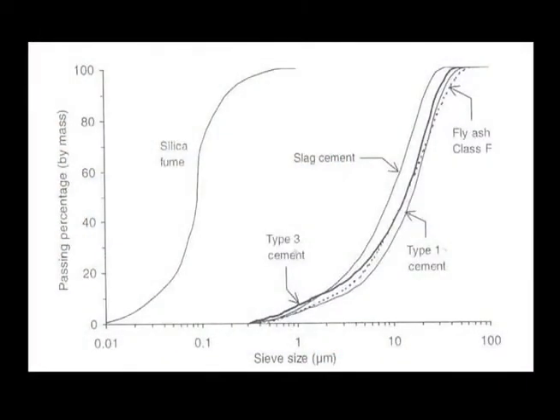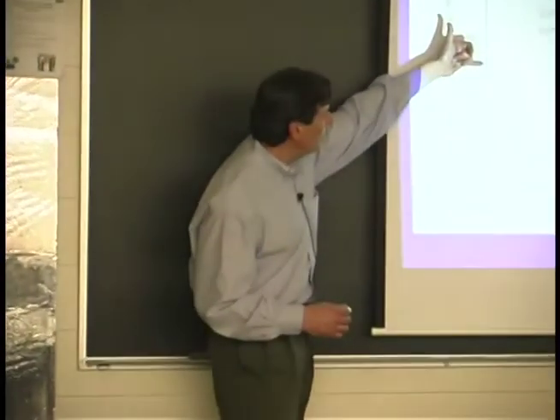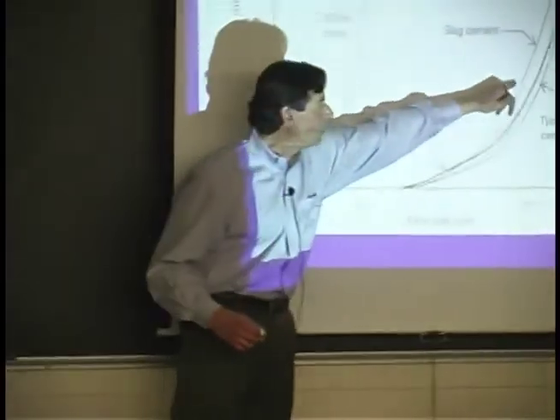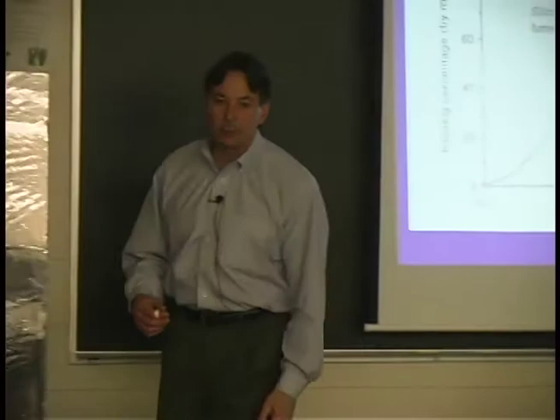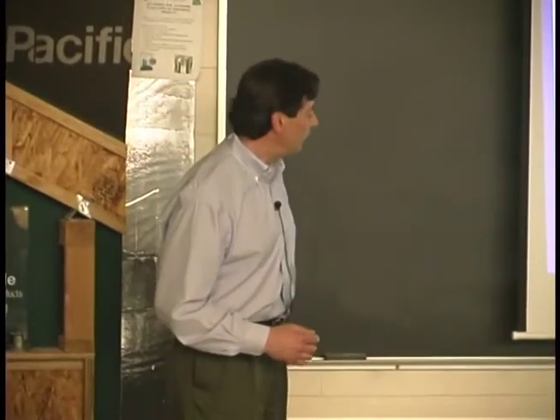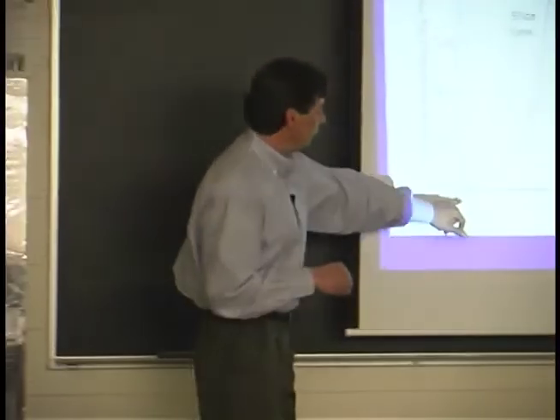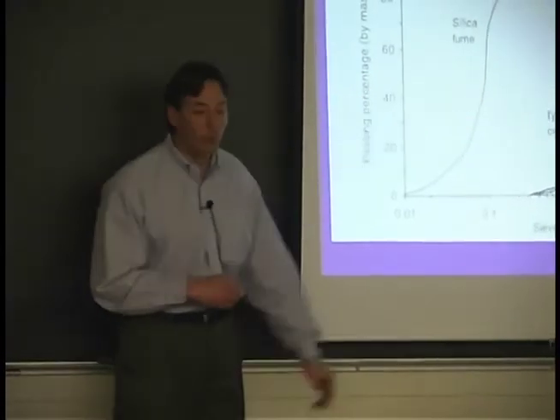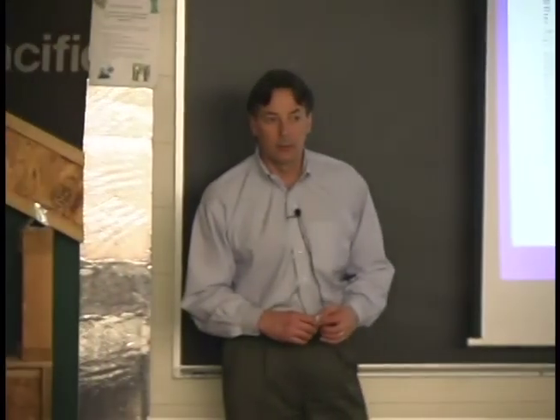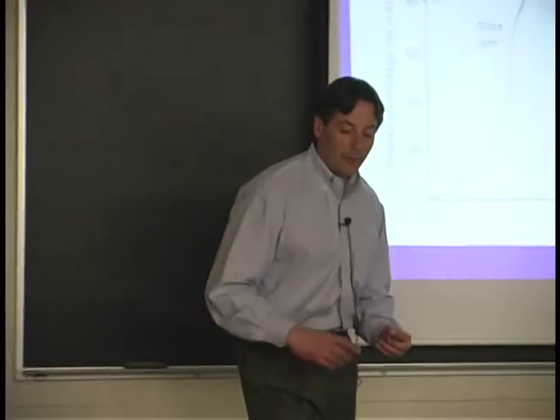Slag, fly ash, two different types of cement, they all basically have the same particle size distribution. If you look at the D50, 50% of the particles, the D50 is probably about 12 micron, 13 micron, somewhere out there, 10 to 12 micron. The D50 of silica fume ends up being about 0.1 micron. Very, very fine material.